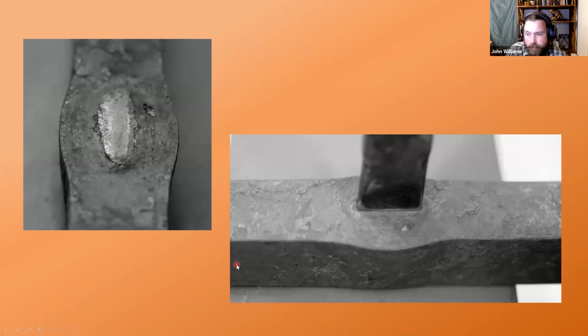This looks like it's out of sequence. The punching, when you're done, you're going to compress the metal down to nearly the bottom of the stock. And when you do so, you're going to see some work hardening and evidence on the backside of the stock. And you're going to back punch that. Some people call this a bullseye. Some people call it a halo. And you're going to punch the majority of the punching with this style of punching from the top side, and then back punch the last little bit through, and that'll remove your slug.